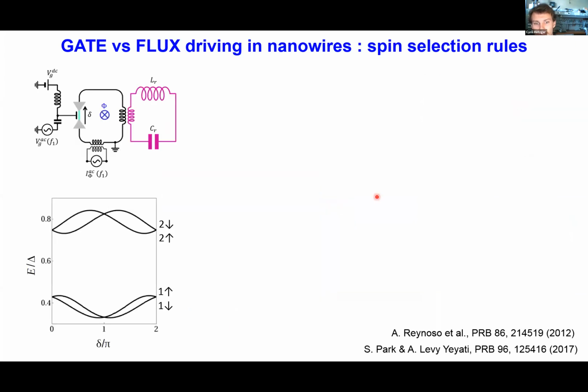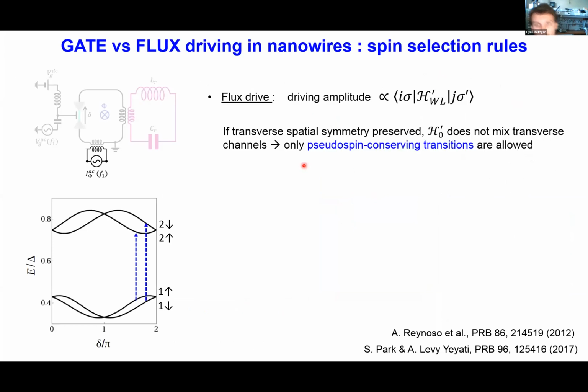So we realized that in this system, if you drive only through flux in a fully ballistic model where the transverse spatial symmetry of the nanowire is preserved, the current operator does not mix transverse channels and only spin-conserving transitions are allowed. So you would only be able to excite these transitions from 1 up to 2 up or 1 down to